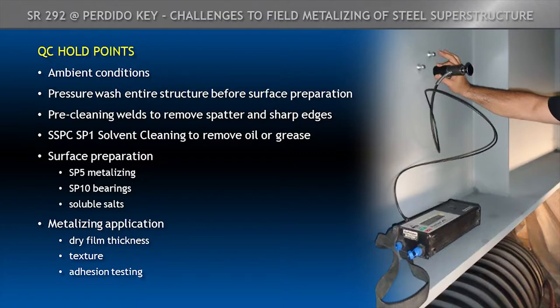We did pressure wash the entire structure before surface preparation, and then we did some pre-cleaning to the welds to remove spatter and sharp edges. And the other thing that the FDOT spec allowed us to do was to make sure that the flame cut edges or the hardened edges were properly prepared before blasting so we could achieve the proper surface profile.